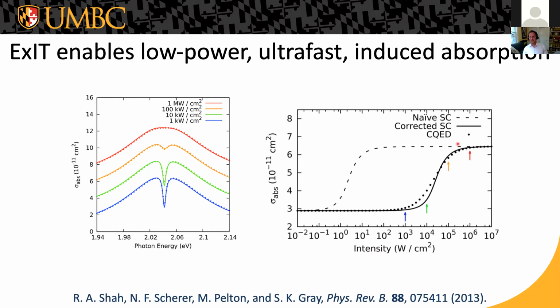in the nanowatt regime. And it would be ultra fast too, because the recovery time of this system is in the picosecond or sub-picosecond regime. So you could have an ultra low power, ultra fast, and really nanometer scale optical modulator where you could control the transmission of light through the system with a very low power control beam. And this would be an important ingredient in future all optical information processing. We have an ultra small all optical modulator.